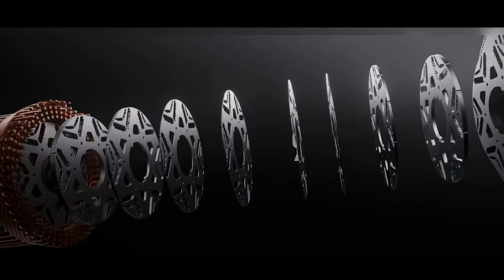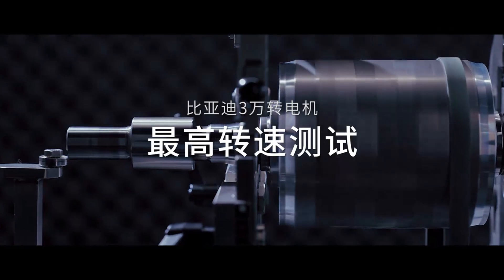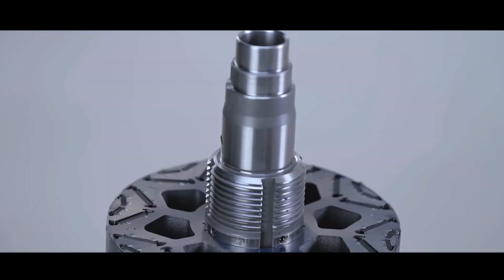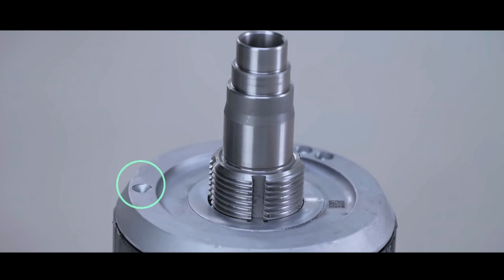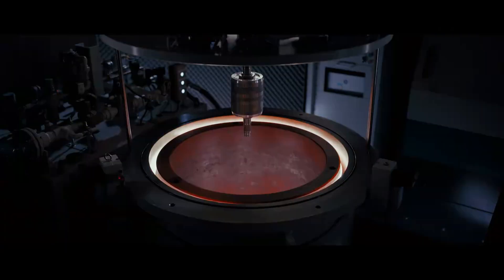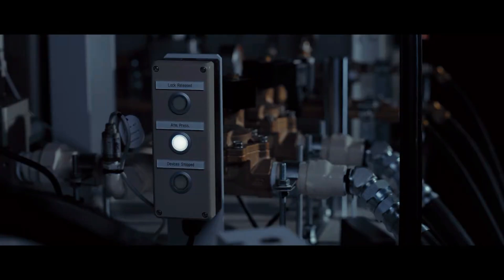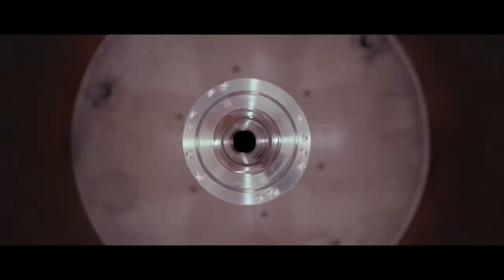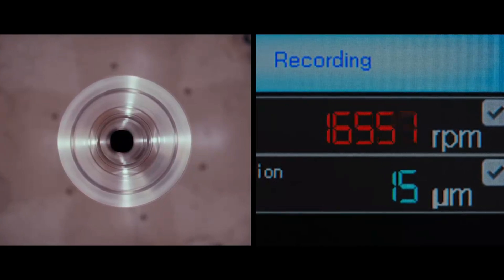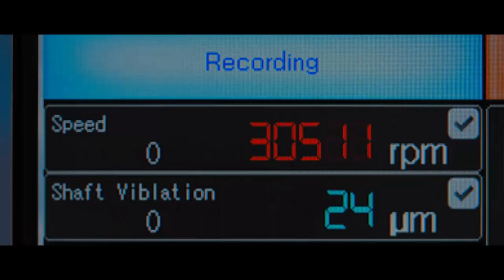BYD shared several unique challenges faced due to ultra-high speeds. First is the permanent magnet fixation problem — at the extreme speed of 30,000 rpm, centrifugal forces are too great for conventional fixation methods, so BYD had to develop special expansion layers to secure the rotor. Second is dynamic balance adjustment. BYD specifically developed high-speed balancing machines — essentially ultra-precise rotor dynamic balancing machines. Before installation, rotors spin at high speeds to release internal stress. These machines achieve precision of 50 mg, 100 times more precise than ordinary tire dynamic balancing, which has a minimum adjustment of 5g — an extremely rare level of precision in industrial fields.